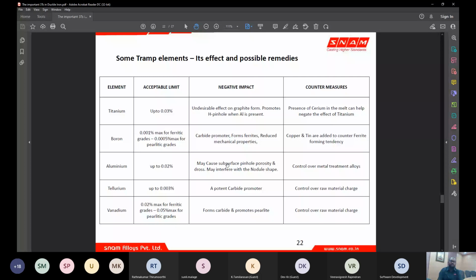And we don't have a facility readily available in any foundry to analyze what kind of carbide it is, say manganese carbide, vanadium carbide, chromium carbide, or tellurium carbide. For us, we do a picral etching or nital etching, and we know it is carbide. So unless we know the source of the carbide, it is very difficult to classify and find the root cause. And if we do not find the right root cause, we'll land in different problems. So it is very essential to have knowledge and control over all these elements.